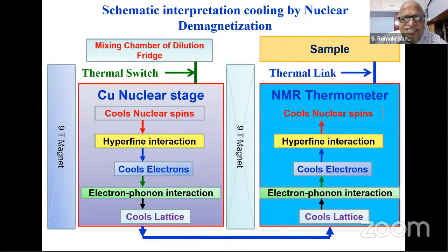So just to tell you the complexities involved, the thermal switch takes the nuclear spins, so you put the thermal switch off and you cool the nuclear stage. By cooling the nuclear stage, you are cooling the nuclear spins. Adiabatic demagnetization cools only the copper nuclear spins. Hyperfine interaction cools the electrons, and the electron-phonon interaction cools the lattice. And how do we measure the temperature? The cooled lattice, via electron-phonon interaction, cools the electrons. The cooled electrons, via hyperfine interaction, cool the nuclear spins. So here you're using a platinum NMR thermometer to measure, and here you're using the copper stage to go down to low temperatures.